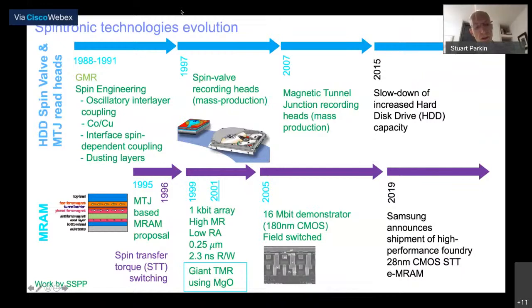So MRAM, we proposed it in 1995. We actually demonstrated that the concept worked just a few years later in 1999. And with the discovery of giant tunneling magnetoresistance in magnetic tunneling junctions using magnesium oxide tunnel barriers, we could then build in 2005 a 16 megabit device fully integrated with CMOS, demonstrating its potential. However, it has taken another decade before MRAM has become essentially a high-performance foundry offering from Samsung, which was announced last year. So I think this was a major achievement.